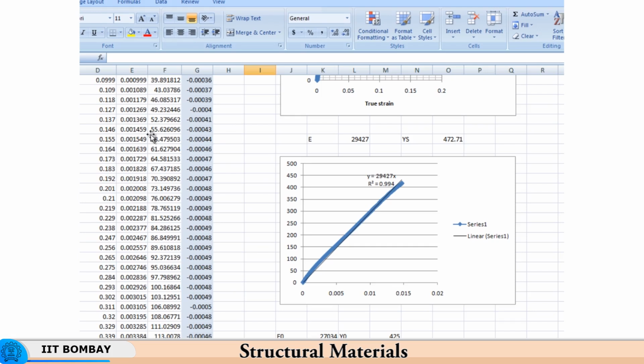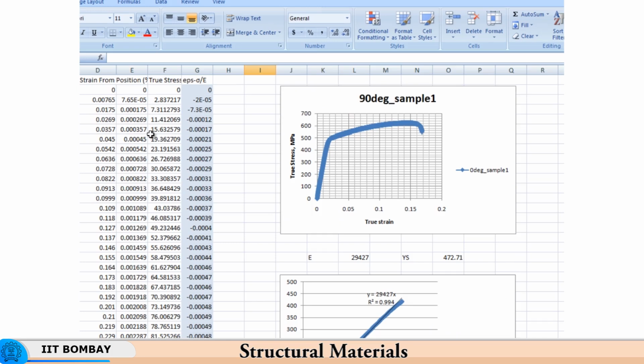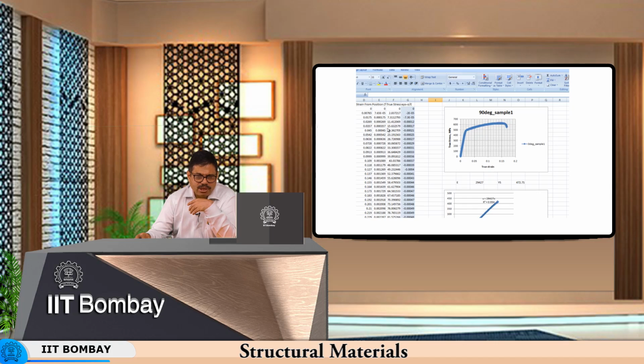So, now you get the value of E, and then you plot these terms epsilon minus sigma by E. So, what it means is that supposing I am trying to evaluate this as a possible yield point for the material. So, I draw a line parallel to this line, which let us say hits the x axis here. So, now I have this as the recovered elastic strain. So, this is equal to sigma by E. E is the Young's modulus, and sigma is the stress over here. So, sigma by E is the recovered elastic strain, and so what I am left with here is the plastic strain. This is the plastic strain, right, and this plastic strain has to be 0.2%.